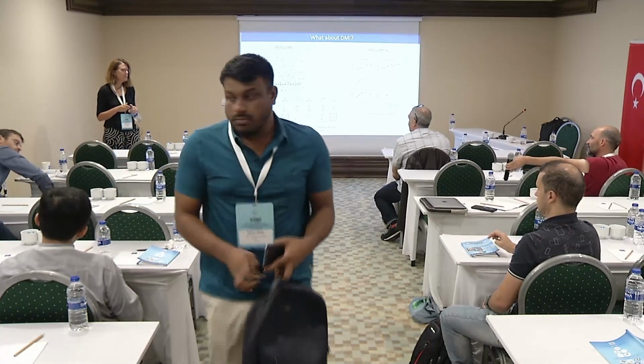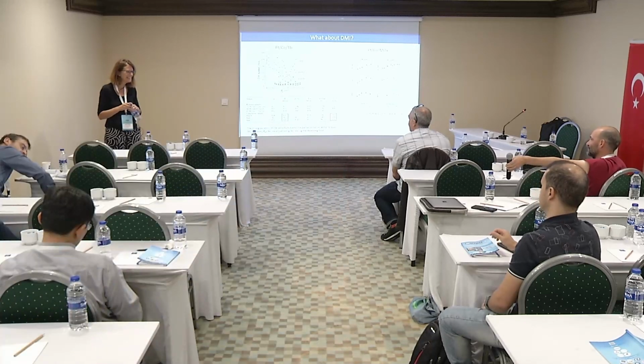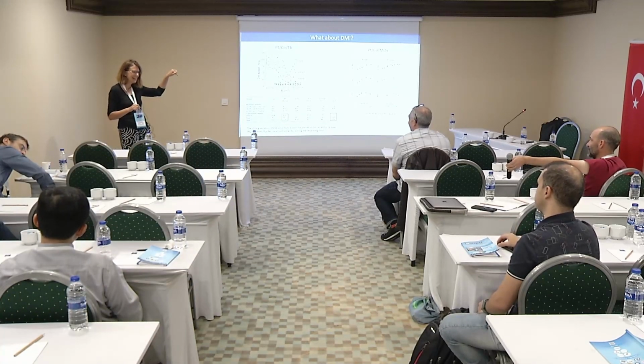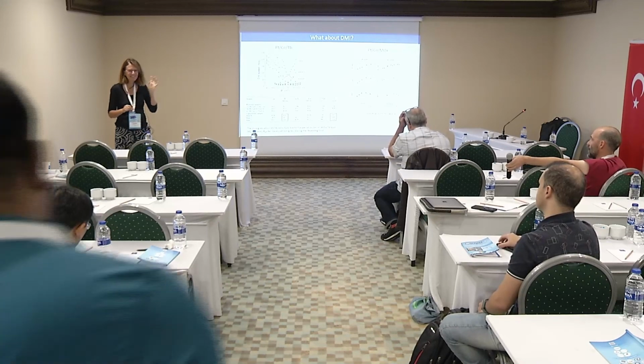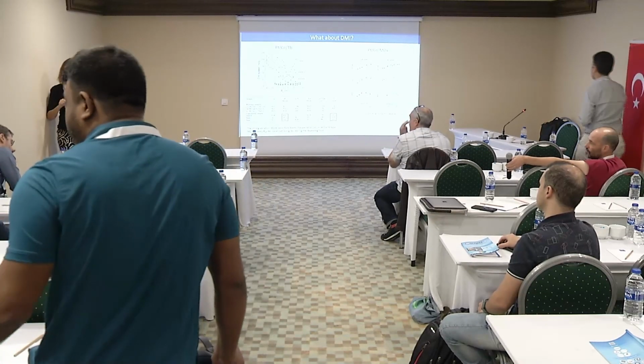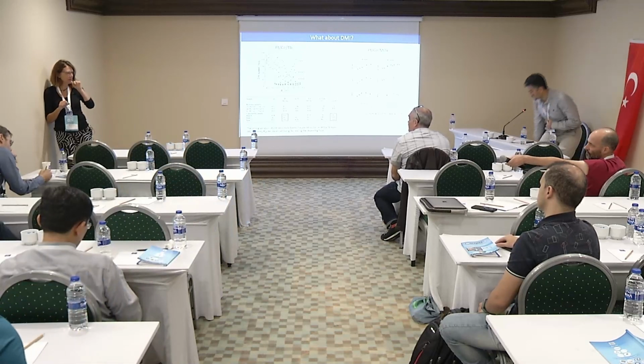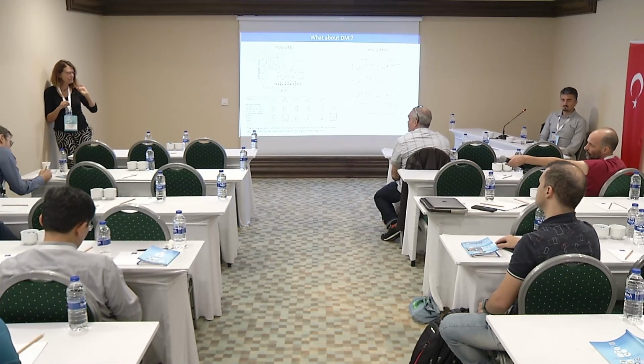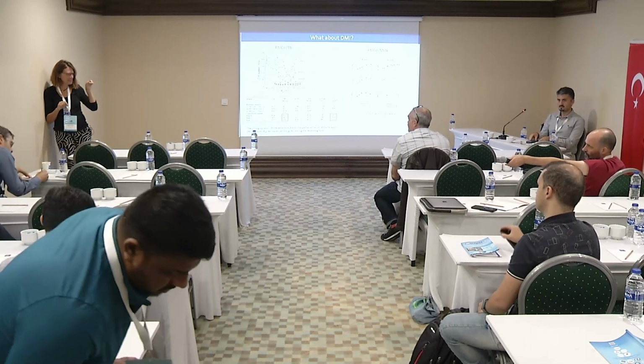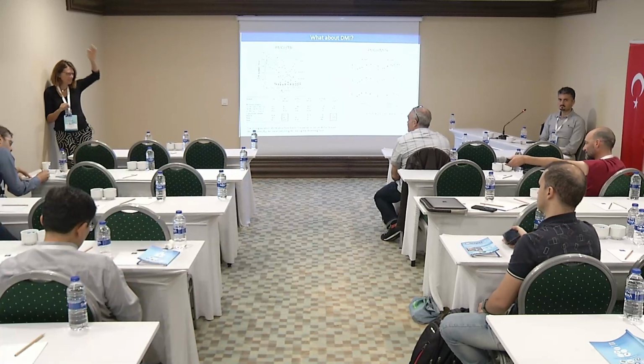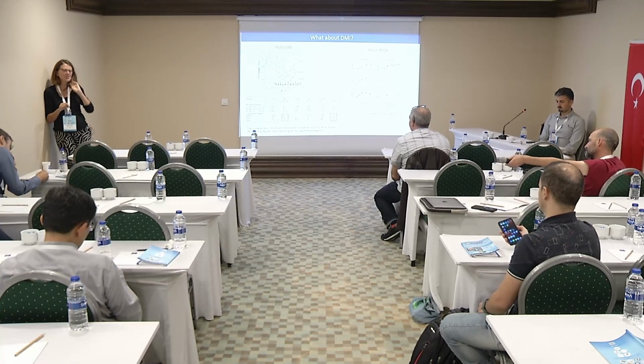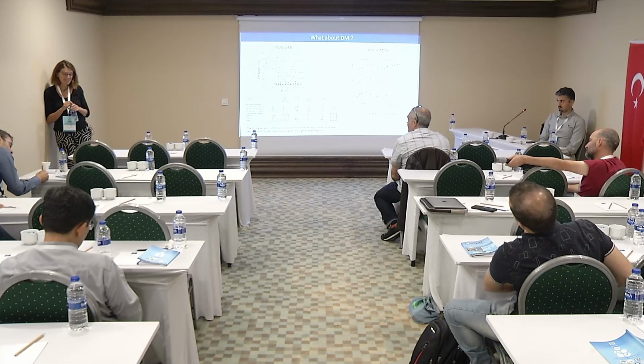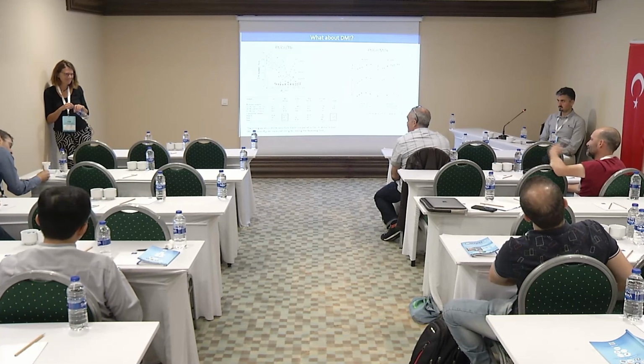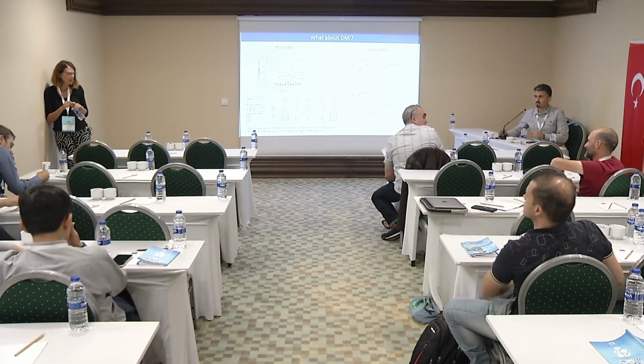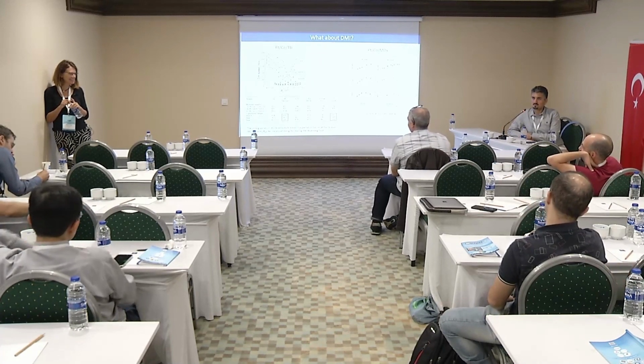We haven't done it, because the problem is that measuring the damping is not so easy. And then measuring the damping under an electrode is harder still. The only times that we manage to measure damping is by domain wall speed measurements in a sample that has very little creep regime, so that you manage to get the slope of the flow regime. Of course, I would expect a change of the damping, but I don't know how to measure it actually.